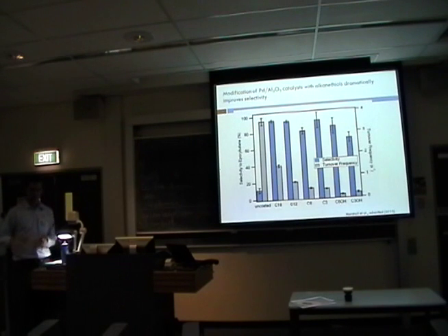And the reason for that is that we're occupying catalyst sites with our self-assembled monolayers. So that's not a big surprise, but we were expecting an orders of magnitude drop off in the reactivity, and instead we only get a very modest drop off in the reactivity with the self-assembled monolayer. But maybe more interesting is that you actually get a much higher reactivity, for example, with a long hydrocarbon chain than with a short one.